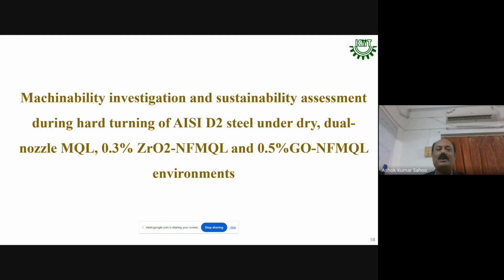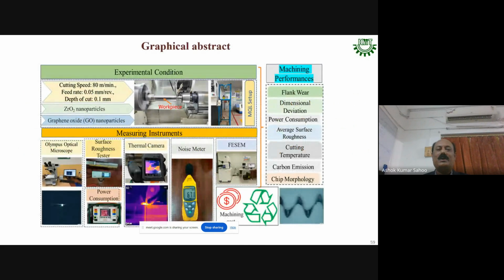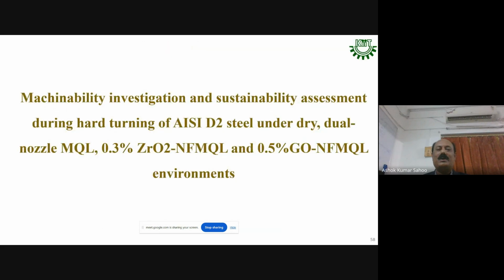The machining of this workpiece material is operated under a dry environment and a dual nozzle minimum quantity lubrication environment. That means double nozzles are applied. One is ejected at the flank wear rubbing zone and another is ejected at the crater wear surface, at the chip tool interface. And also the nanofluid minimum quantity lubrication environment with ZrO2, zirconium oxide nanofluid, and graphene oxide nanofluid environment. So 4 cutting environments are utilized for sustainability.